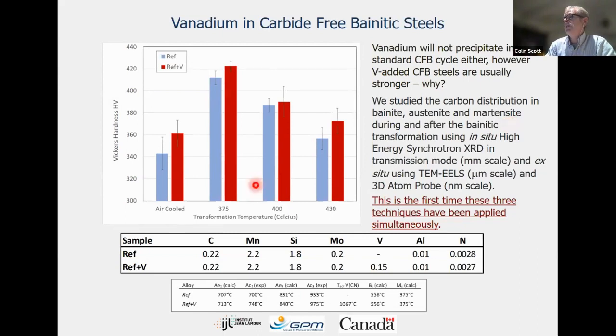So here's some hardness data from the composition I'm going to talk about today. This is the air-cooled hot rolled condition, and then this is the transformed condition, transformation at 375, 400, and 430 degrees C. And you can see the strength actually increases as the transformation temperature decreases, but the vanadium does give you a benefit at all of those temperatures.